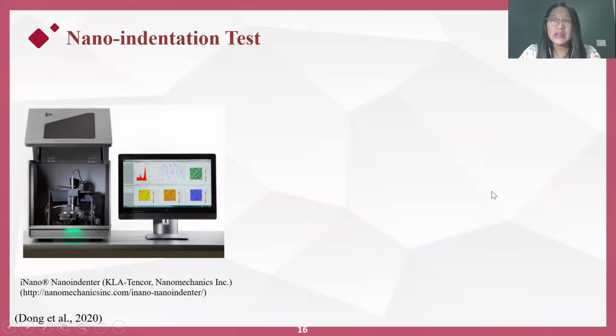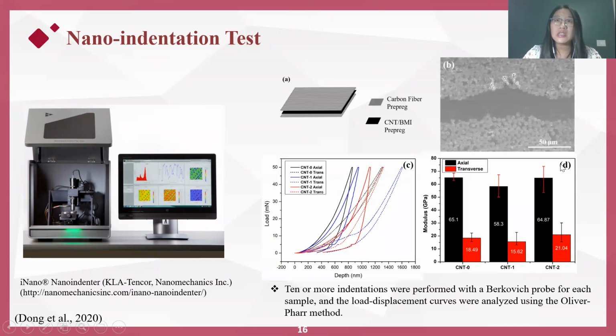To further study the mechanical properties of nanocomposites, we have conducted a nanoindentation test to reveal more detailed microstructure property relationships and also provide nanoscale insights of elastic modulus and indentation hardness. The as-collected CNTs were saturated in a BMI solution and then sandwiched in between the unidirectional carbon fiber prepreg before curing.